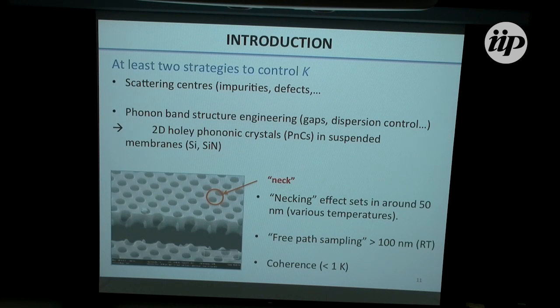So in terms of phononic crystals, there are at least two strategies to control the thermal conductivity. One is based on controlling the placing and number of scattering centers, be these impurities or defects. And the other refers to changing or engineering the phononic band structure so that you can have gaps or regions where phonons cannot propagate, or regions where phonons travel slowly.